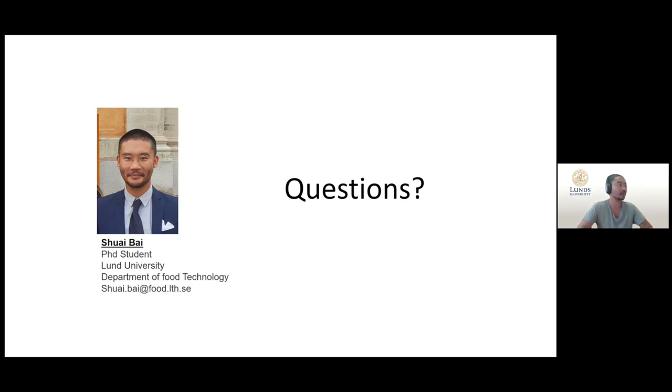Try Emanuel here maybe I can give some details. The scans that were showed here that you saw, they took, we really pushed the resolution, so with the lab-based scan it took around nine hours actually. But I mean this is in a lab-based environment. If you go to synchrotron you have higher flux so you will be able to image much faster. And exposure time I will need to double check but I think it was between five and 12 seconds or something.